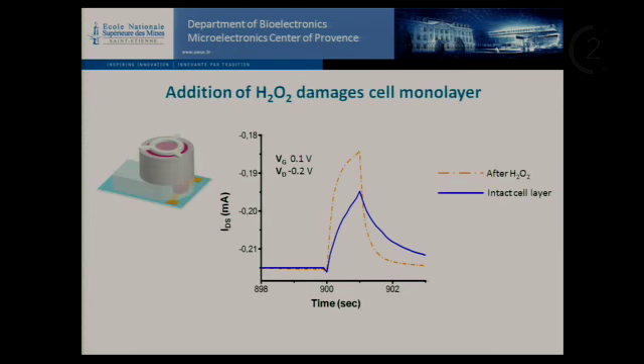This plot better shows the comparison between the healthy cell layer response and then when the cells are exposed to hydrogen peroxide. We see that although the hydrogen peroxide is not completely destroying the cell layer, we are destroying the ion barrier, or the barrier for transport of ions.